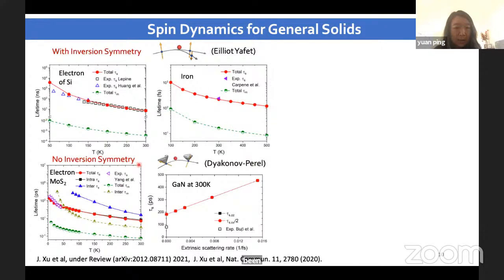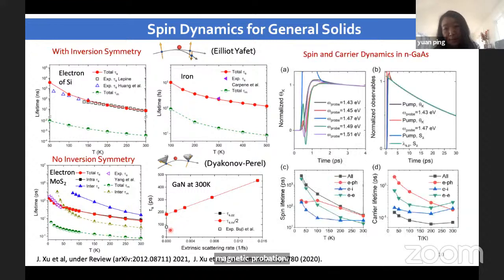We also show systems without inversion symmetry, because broken inversion symmetry will break the Kramers degeneracy between the up and down spin, which will create an internal magnetic field to cause spin precession. And this will also scatter with phonons and the environment. So we show you examples of MoS2 and gallium nitride. And I want to note the examples I show here are for intrinsic systems, where we generate a spin imbalance by circularly polarized light or magnetic perturbation. And I'll also compare it well with experiment.